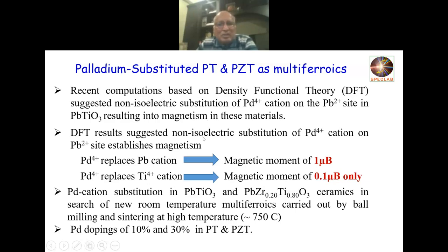If they substitute Pd4+ in the A site, then the resulting material will show magnetism. DFT calculations also suggested that if Pd4+ replaces the Pb ion, that is the A site cation, then the magnetic moment will be something like 1 microBohr magneton. But if it replaces the Ti ion, that is the B site, then the magnetic moment will be only 0.1, much less compared to this one. So based on those theoretical computations, we decided to synthesize the material with the palladium cation substituted in the A site, that is the Pb site, in both of these materials. We used ball milling, and the process is the same ceramic processing, but the dopings we chose were 10% and 30% of palladium in these materials.